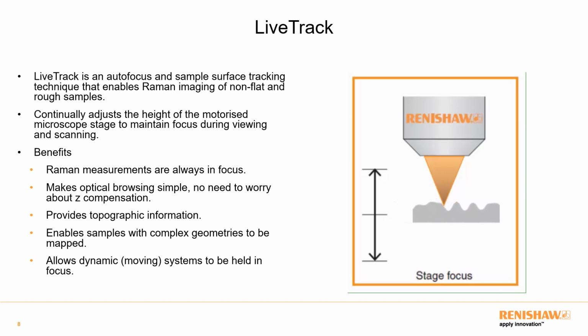Because we're moving the stage up and down, and we record the position of this stage, this allows us to get topographic information from the sample. So we're able to see what the change in height is of the roughness, things like that. But fundamentally, this is a really nice tool for measuring samples with complex geometries. So you can measure anything from a glass slide down to macroscopic objects. One of the examples I'm going to look at in a minute is a rat mandible. You can also measure things like battery electrodes, which are very rough. And again, I'll show you that in a second.